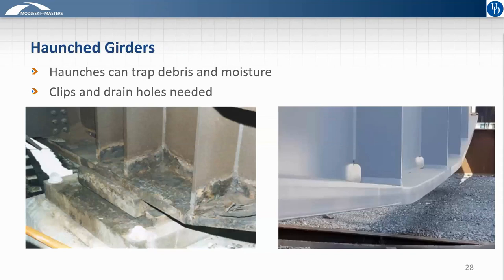Areas where this often happens are in haunched girders. If you're not careful with the detailing, these areas will tend to collect debris. So on the left is an uncoated weathering steel bridge that has had a lot of debris collect over the years. I think it's been cleaned off for the inspection in this case. But you can see where it was and the sort of continuous corrosion that's occurred there. So you need, as a designer, to always think about when you're adding stiffeners and when you're detailing your girders, where debris can collect, where corrosion can be trapped, or where moisture can be trapped and cause corrosion. The image on the right, although it's of a painted bridge, exemplifies one approach to this would be to provide generous clips and copes at the bottom of your stiffeners, in particular in the haunched area, to allow water and debris to not collect.